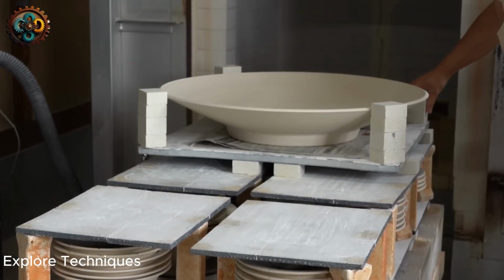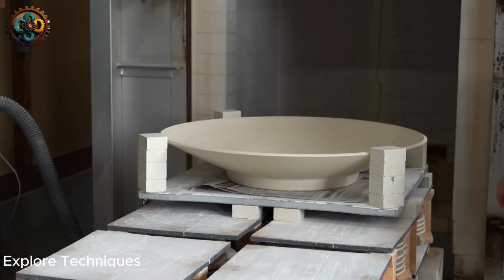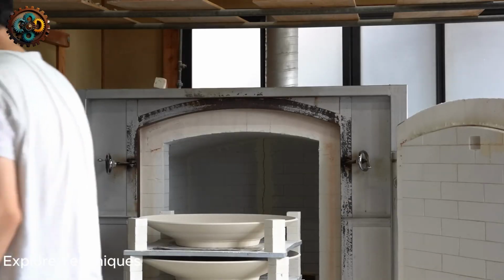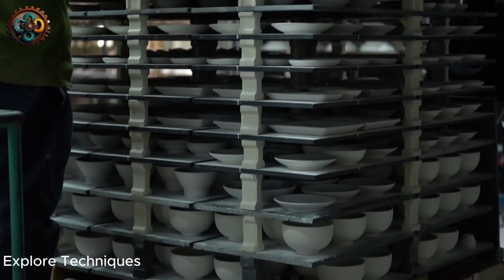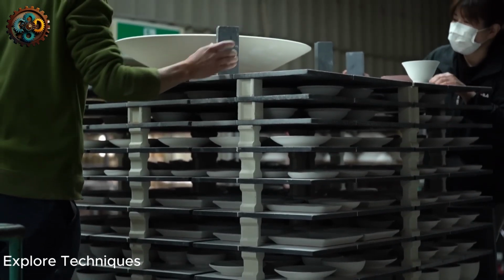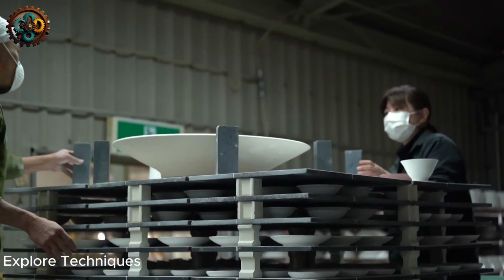After the product is completely dry, it will be put into the kiln for the first firing. The kiln is an indispensable part of the ceramic making process and can reach very high temperatures, from 800 to 1000 degrees Celsius. This process, called pre-firing or bisque firing, makes the clay strong and durable, creating a porous ceramic product that still easily absorbs the glaze during the next step.